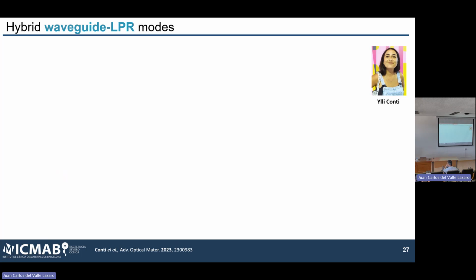Normally, once we deposit the particles, we cover them with another layer that is matching the refractive index of glass. So these systems are isolated. This is the only way to see the lattice resonance. When Ylli, my PhD student, joined the group, we were interested in leaving the cavity, leaving the metasurface open, because otherwise there is no way to access the chemical space of the surrounding environment if the particles are trapped within, in our case, the PDMS layer.